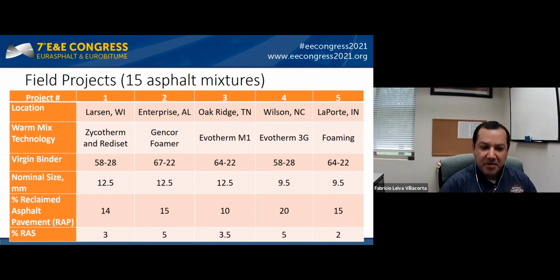Pretty much all the mixes in the United States have a RAP or reclaimed asphalt pavement. The minimum we had was 10%. And with regards to asphalt shingles, those range from 2% all the way up to 5%. And those were the ones that we were mostly interested on.